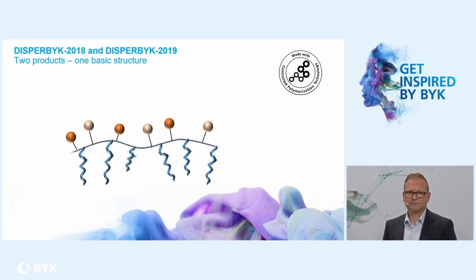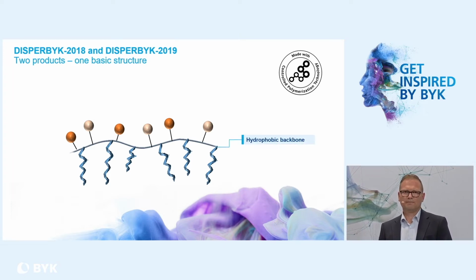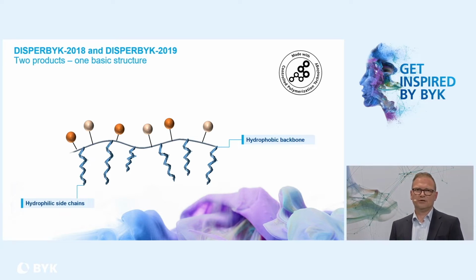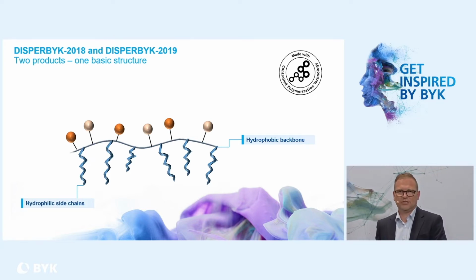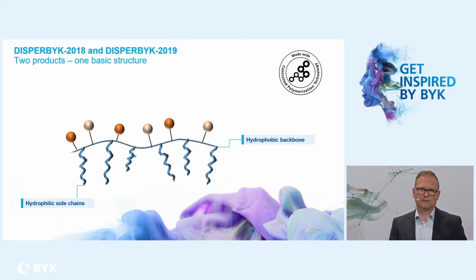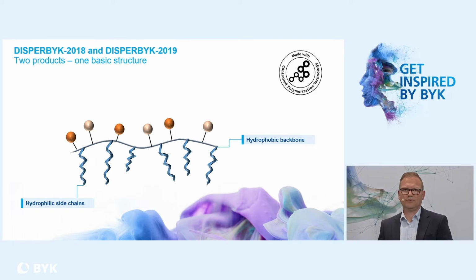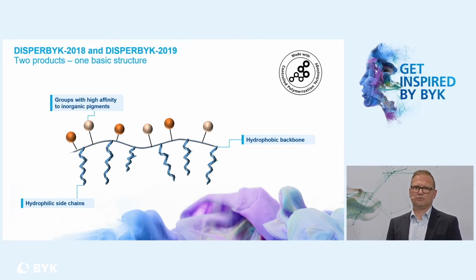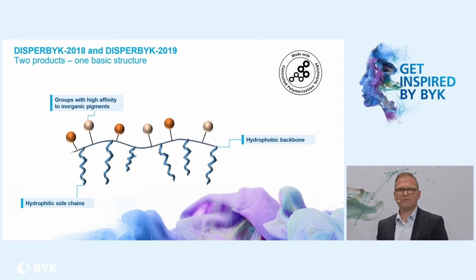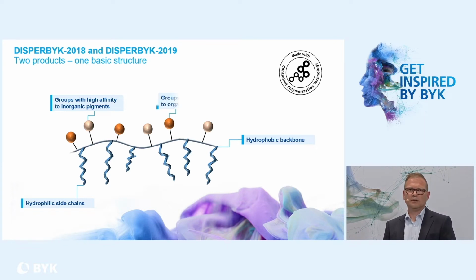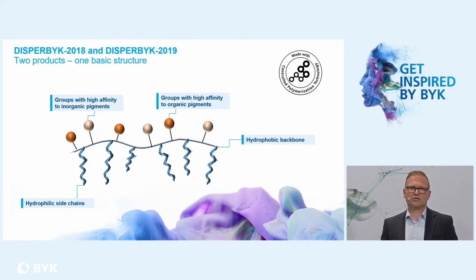But what is behind? We have one basic structure for both additives. We have a hydrophobic backbone, and then hydrophilic side chains. You need in water-based formulation these hydrophilic side chains for the stabilization, for the steric stabilization of the pigments. The side chain has to be soluble in water, compatible with water. But on the other hand, you need a high affinity to different pigments. And therefore, we have groups with a high affinity to inorganic pigments. But in this molecule, we have something more. We have also in the structure pigment affinity groups for organic pigments,